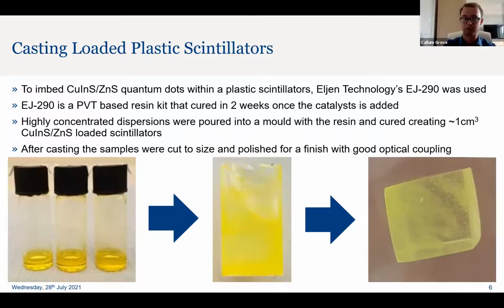We were interested in the loading rather than the shape, so we had just centimeter cube molds. The way that we would cast a scintillator is we'd first dissolve quantum dots into a small amount of toluene. Compared to 5 milligrams in 5 milliliters in the liquid dispersion study, this is a picture, on the left here, of 40, 80, and 120 milligrams in about a quarter of a milliliter of toluene. So they're quite highly dispersed, and then we put that into the mold with the resin, mixed it together, cast it, and produced this at the end of the 2 weeks.